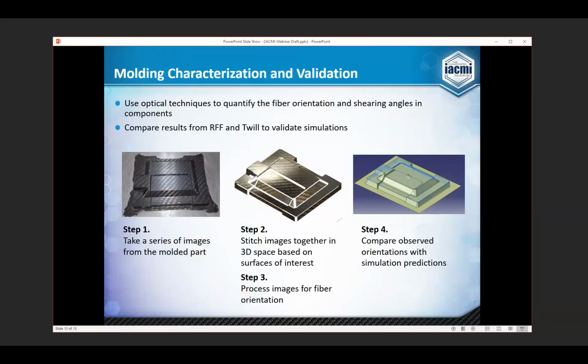Because if we can understand how the material is going to form, and then we understand how the formed material is going to behave mechanically, then if we understand which angles our fibers are at, we have a very high confidence that we're going to be able to predict part performance and use that to drive design, to be able to optimize to the correct fiber orientation, to zero in on the right fiber volume fraction that gives us the right performance characteristics of our part, and really have a leg up in our initial prototype to have that good first trial.